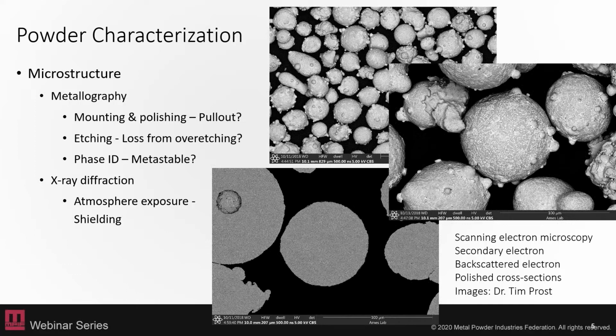And those happen when smaller particles are recirculated within the atomization chamber. Those particles can come back up and then be entrained within the atomization stream itself, and then deposit on those larger particles as they are cooling and being formed. And so you can see even just from this image that those powder features are going to have an effect on how those particles pack together, how they flow together, how they might sinter together if you're using a binder jet AM method.